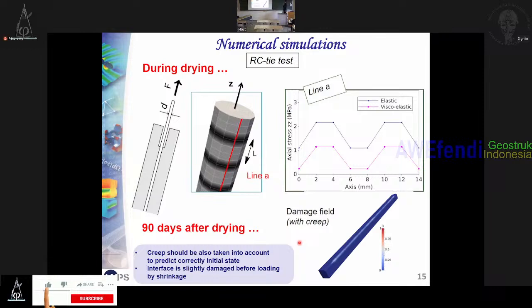If you do the numerical simulations, here it's just before the application of the force. You can see that you already have stresses inside the specimen. Here is an elastic calculation, without creep, and here is the one taking creep into account. As I said before, if you do not take creep into account, you overestimate the stress inside the concrete. You can also see that you already have a little bit of damage because of the concrete shrinkage being restrained by the rebar.